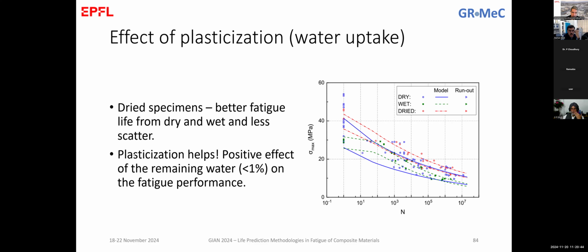And here is the conclusion that we ended up with in this case: this drying procedure allows the plasticization that is happening to the material due to the water intake to actually come back, always to the same discussion that we had before. There is a region here that is caused by this plasticization, and this helps in the delay of the failure of the material. So we've seen that this helped in the static loading, and this helped also in the fatigue loading.